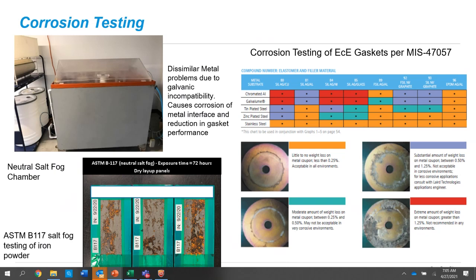But if you look at that lower left-hand corner, you can really see the problem. This is standard carbonyl iron loaded rubber, and after only 3 days in a salt fog chamber, you can see the level of corrosion. The standard filler for these magnetic absorbers is carbonyl iron powder, and it's pure iron, so it will oxidize. And when it oxidizes, two things happen. One is it looks like you see in that picture, which isn't very pretty, but two, iron oxide is not magnetic. So you've got two problems. One is a cosmetic problem, but more importantly, as it continues to rust, the performance of the absorber will degrade. So that's just general corrosion of filler materials.